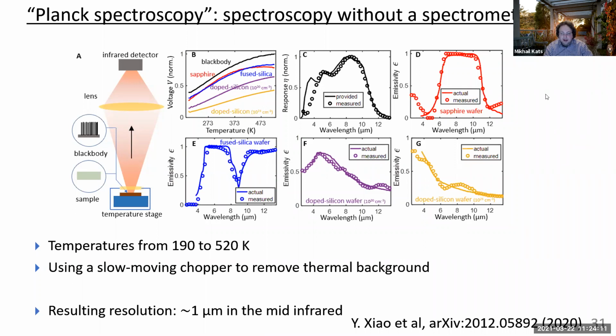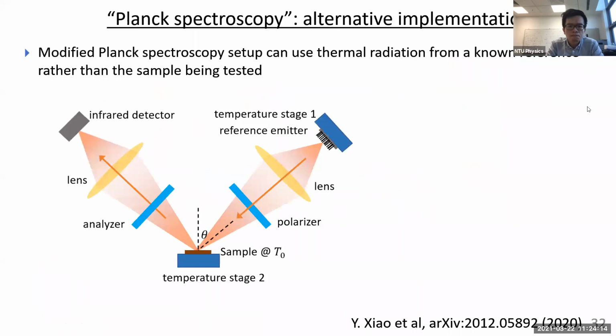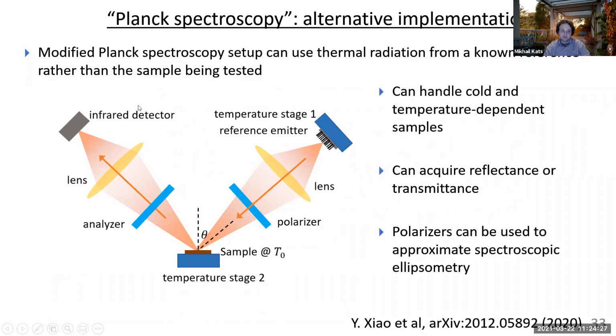All right. By the way, even though I just said that you can't do this for emissivity that changes as a function of temperature, there are modified approaches that would enable you to do those kinds of measurements. So here's a modified Planck spectroscopy measurement, where instead of using one temperature stage and using the thermal emission from the sample, you could have two temperature stages, and you could have your reference with the known emissivity sitting on the temperature stage, and you could reflect off of the sample or transmit through the sample. And in that case, you're doing something quite similar to conventional spectroscopy. You can imagine putting polarizers here and doing ellipsometry-type measurements and so forth. And in that case, you can, of course, handle temperature-dependent emissivities as well. In this case, reflectances or transmittances.